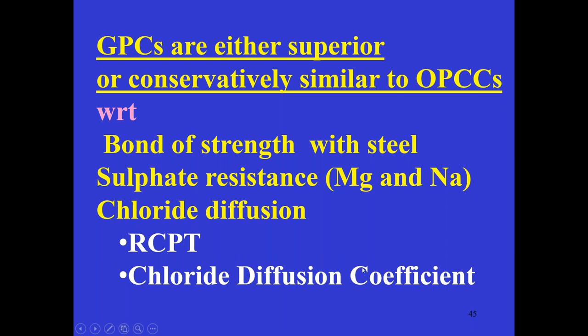This is better. Chloride diffusion coefficient we can measure. Okay, this is simple. They are simple calculations, simple measurement. Only time involved is little more. And we have to break open the specimen, study what is the thickness to which the chloride has entered. So that's why, when you do chloride diffusion coefficient, really it is a picture of chloride diffusion, not RCPT at all.